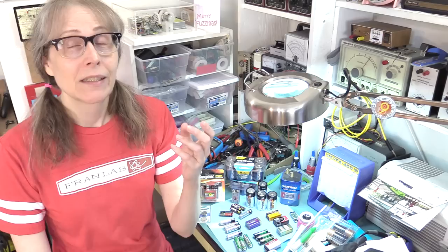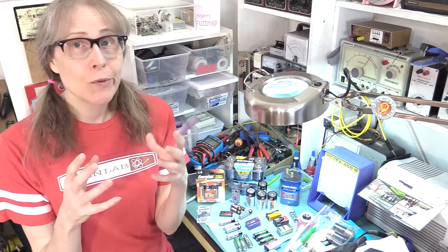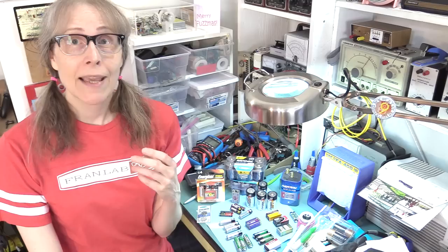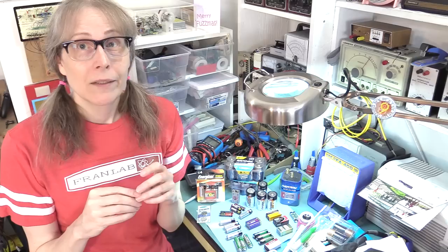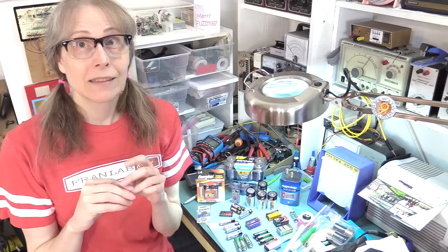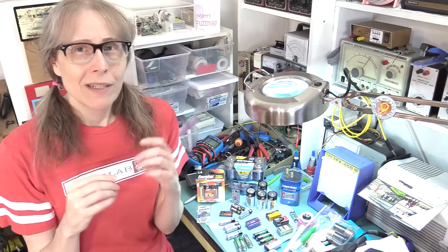It's chemically pretty simple, actually. Alkaline batteries are powered by an electrolyte — usually potassium hydroxide. As the battery loses its power and begins to age, the electrolyte begins to break down and it begins to release H2, hydrogen gas. Over time, if the battery gets to a dead or low-power condition inside the device for long enough, that hydrogen gas builds up and eventually breaks out of the container, and coming out of the breach along with the hydrogen gas is the potassium hydroxide, which then reacts with whatever it comes in contact with — usually the contacts in the battery compartment.